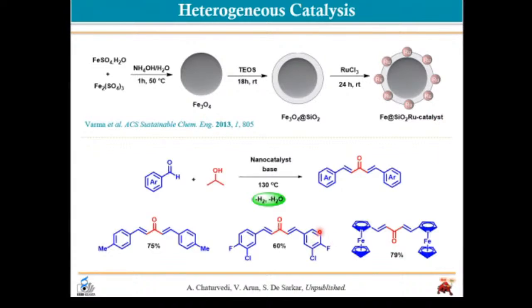And we did one standard reaction. We took isopropanol, and the same concept I have already explained to you. The ruthenium catalyst first forms acetone in situ here. In the presence of base, it will undergo aldol condensation on both sides. So this red part is from isopropanol, and this green part comes from benzaldehyde derivatives, and you see these nice molecules. We prepared them nicely, and he got almost 80% yield. Okay, so this is the thing.